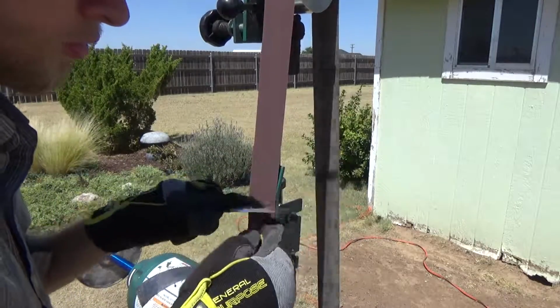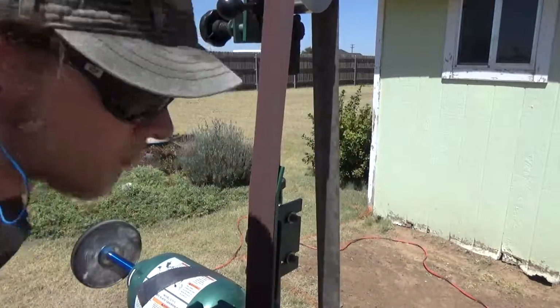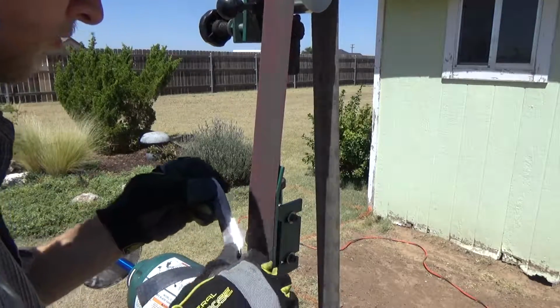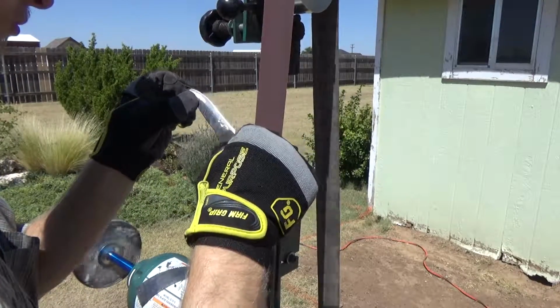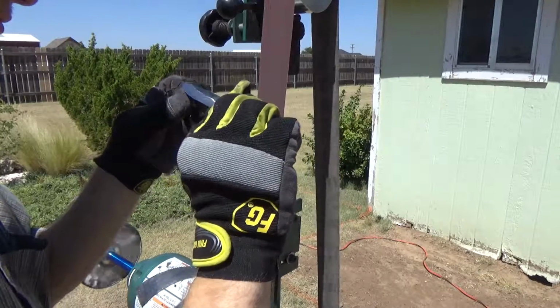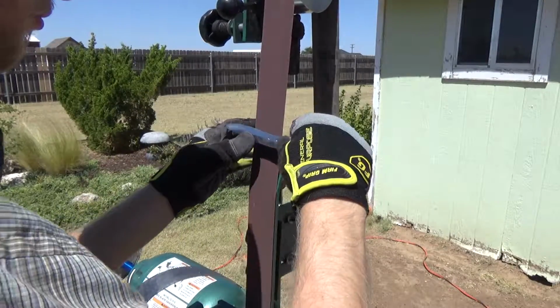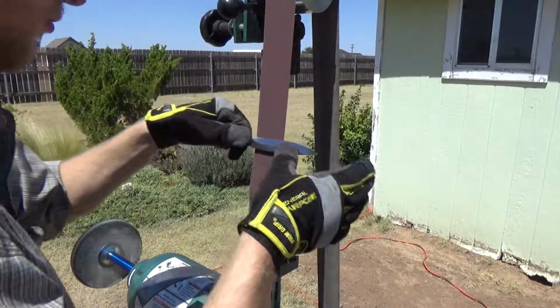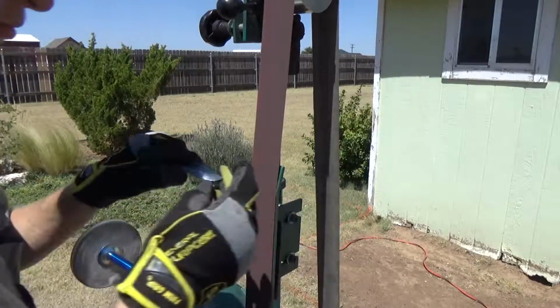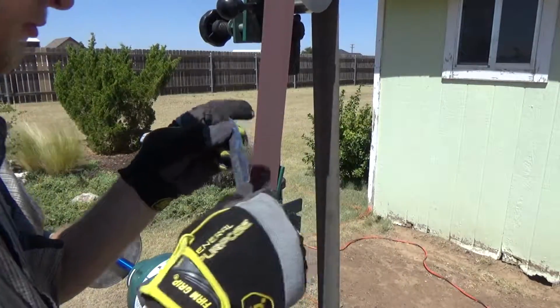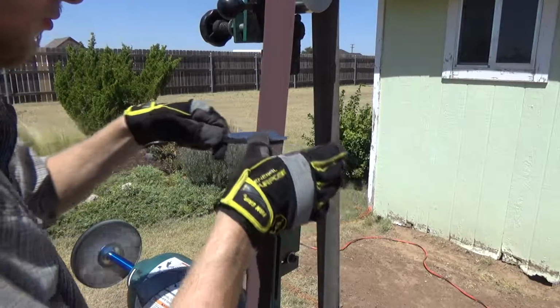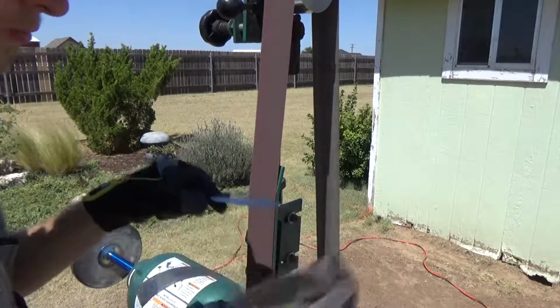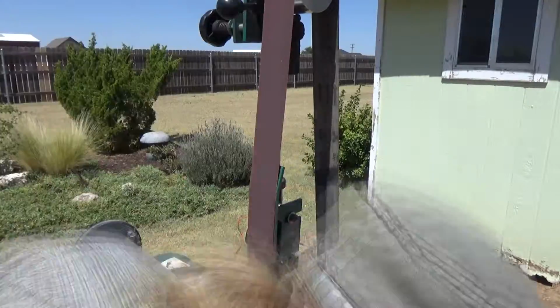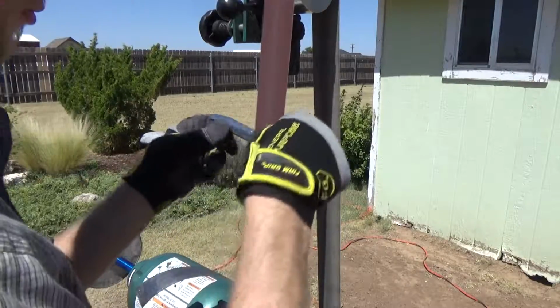I have ruined the temper, to a degree at least, on the tip, which is not necessarily a bad thing because the tip is fairly delicate. It could do with some more toughness, but you really want to be careful with this stuff because you can very easily burn the temper while grinding after heat treat. And one of the reasons to use the slack belt is because it doesn't produce as much heat. It's not as aggressive, meaning you feel like you have to grind a lot more, but it also does not produce as much heat, which makes you feel more safe, so you have to be even more careful about it.